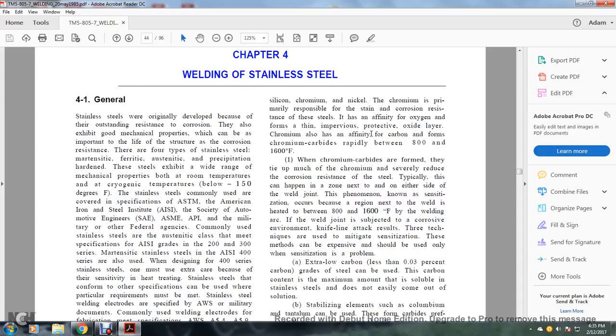Chromium also has an affinity for carbon and forms chromium carbides, which precipitate rapidly between 800 and 1600 degrees Fahrenheit. When chromium carbides are formed, they tie up much of the chromium and serve to reduce the corrosion resistance of the steel. Typically, this can happen in the zone on either side of the welding joint. The phenomenon known as sensitization occurs because the region next to the weld is heated between 800 and 1600 degrees Fahrenheit. If the welded joint is subjected to a corrosive environment, knife-line attack results.